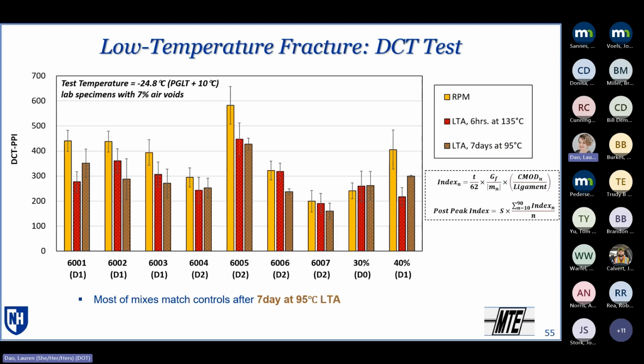So this is a DCT test. The parameter that I'm showing is not the fracture energy, but the post-peak index, the PPI value. So it's a combination of fracture energy and parameters from the post-peak slope, more similar to what you're used to seeing with the flexibility index.